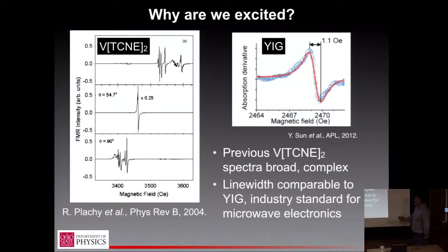So the other half of this motivation comes from this graph, which is a similar measurement on thin film yttrium iron garnet. This is a workhorse material. It's got a lot of recent excitement in the spin pumping field for driving spin currents into platinum and whatnot. But when that kicked off, it was very hard to get research grade YIG because it was essentially an industrial material, like sandpaper. People were just mass producing YIG for use in microwave electronics. So even before spintronics applications, people were very interested in this very sharp microwave resonance to do careful spectral filtering and phase shifting of microwave signals.